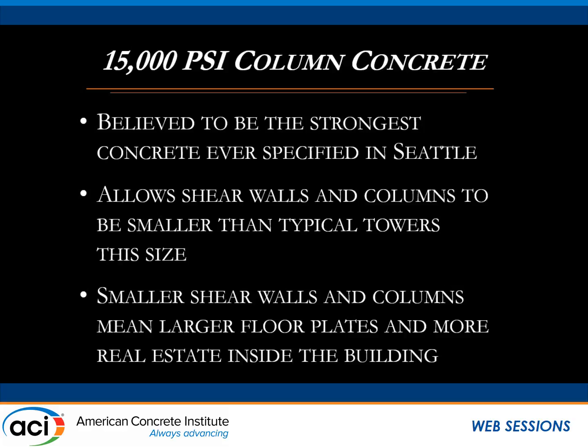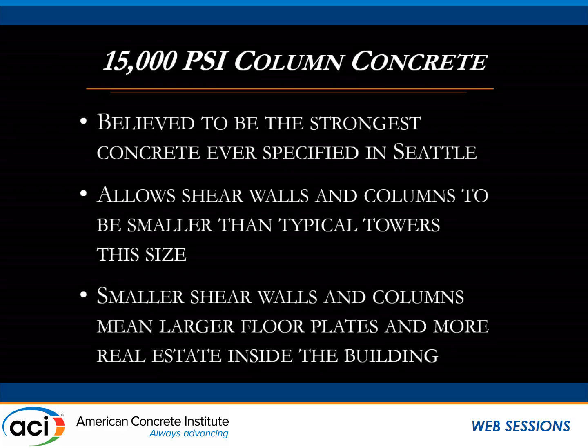So we're very fortunate in Seattle to have a very abundant supply of granite aggregate. It allows us to push f'c way up. So we do. There's no real reason not to. It's available. You can basically increase the net rentable or net sellable square footage, dropping down to the bottom of this slide. That's really the bottom line. You're trying to create more real estate in your building.